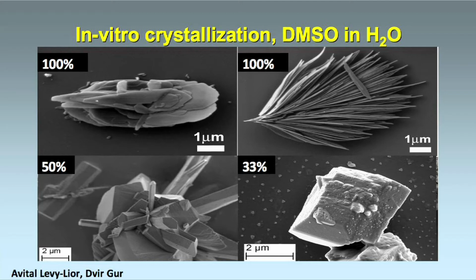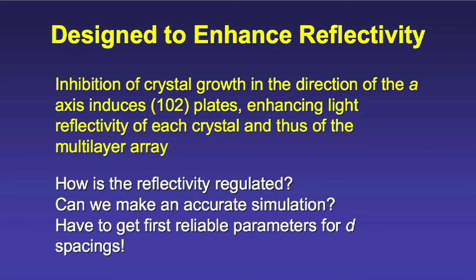And as we go down with the percentage of DMSO in water, indeed the morphology that was predicted theoretically appears, and this is practically identical to the theoretical morphology. So the conclusion is that these crystals are designed to enhance reflectivity, and inhibition of the crystal growth in the direction that is desired produces thin plates that enhance the light reflectivity of each crystal and thus of the whole multi-layer array. But then we can ask, how is the reflectivity regulated? And can we make a simulation of what the reflectivity is? And in order to do that, we have first to get reliable parameters from the system.